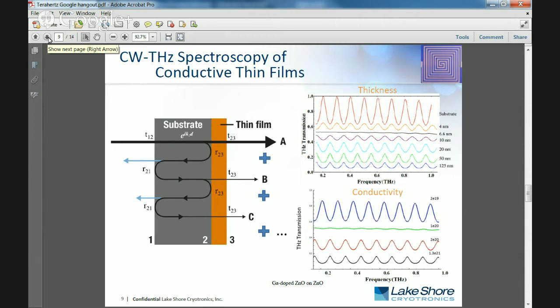What you see is a drop in the terahertz transmission, but you also see a phase change in the interference pattern. And so we're able to extract, with very high precision, the conductivity of these thin films. Likewise, by changing the carrier concentration, by annealing or changing doping conditions, we see this change in the interference pattern. So what we're really doing is using the substrate sort of as a resonator to measure the properties of the thin film on one side of the substrate.